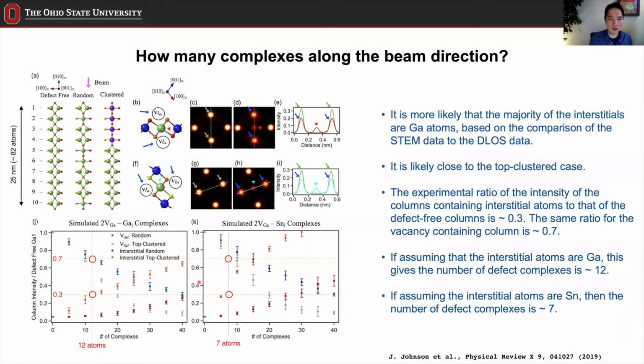But as I mentioned earlier, the signal here is not only dependent on the number of atoms within this column, but also the Z number, the mass of the atom, also affects the intensity. Meaning that if the cation in the interstitial that is placed here is tin, then the intensity is going to be higher. So depending on whether the cation is either tin or gallium, that's going to change our intensity. So we cannot get to a unique solution for the number of atoms that are placed right here. That's the question: whether the cation is gallium or tin, because it can be either way, right?